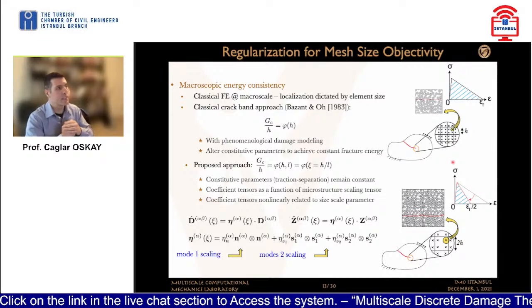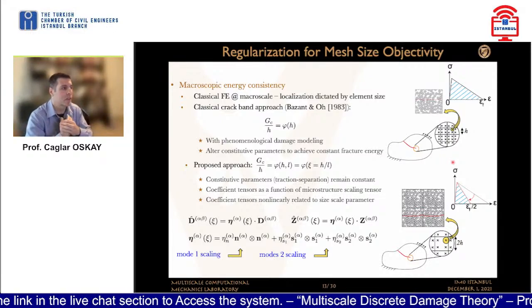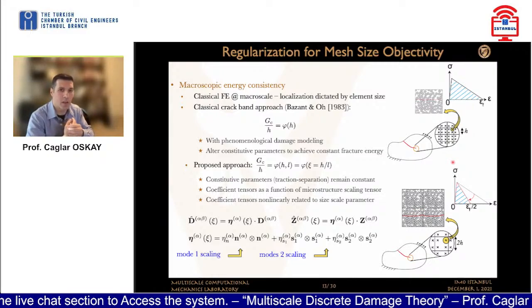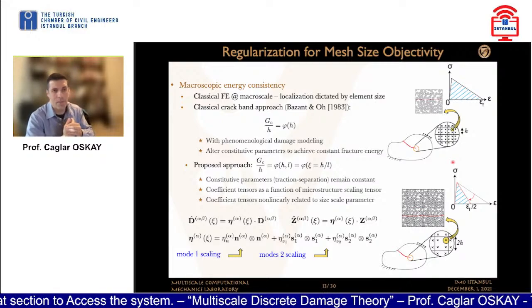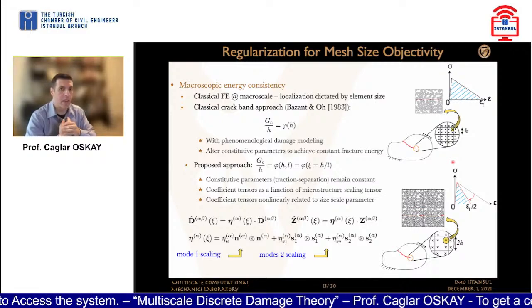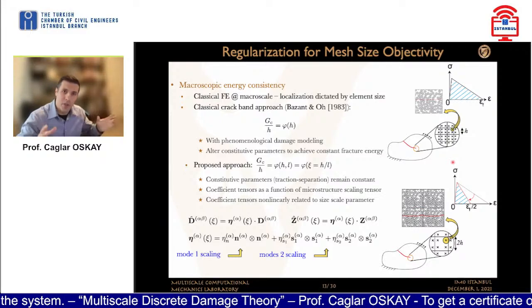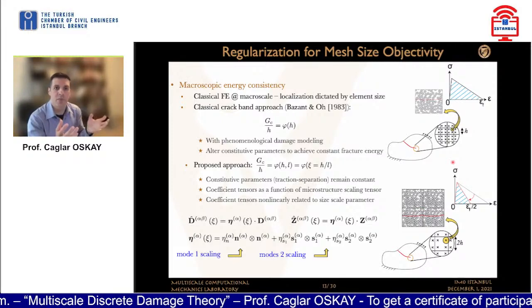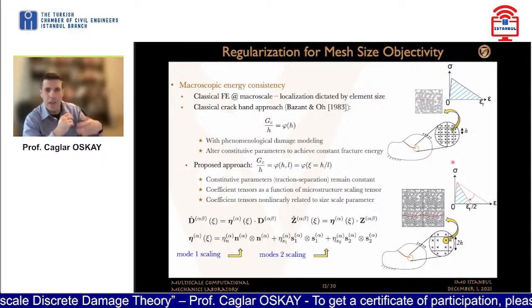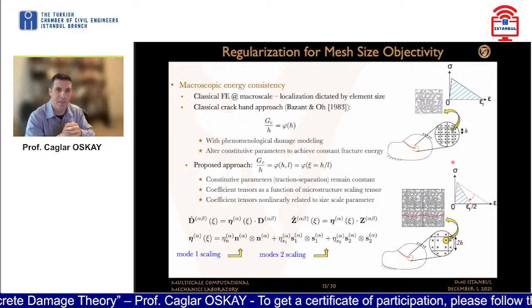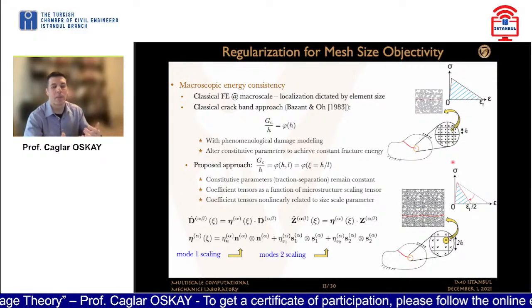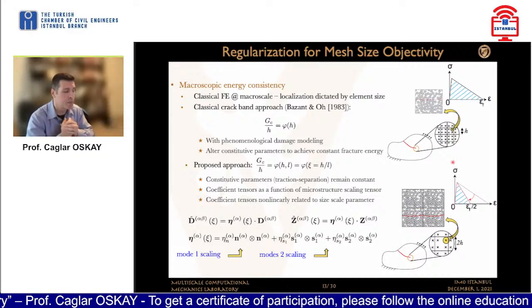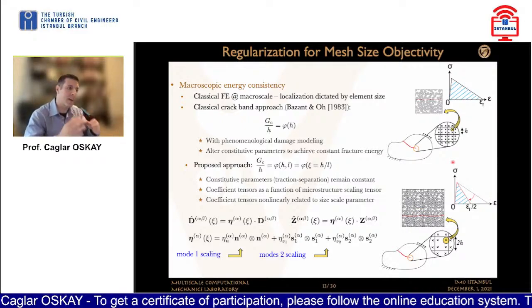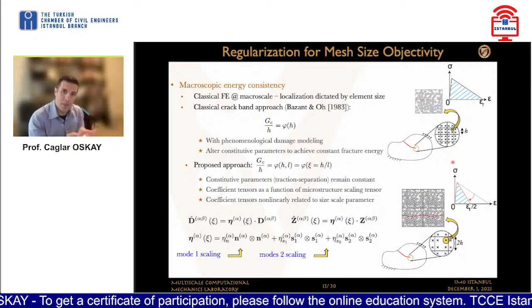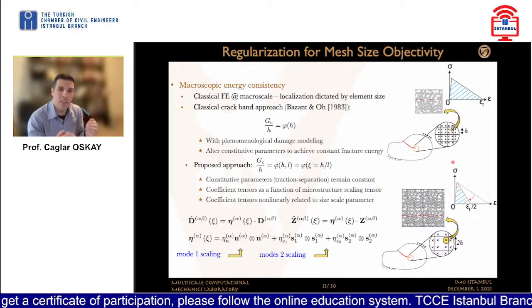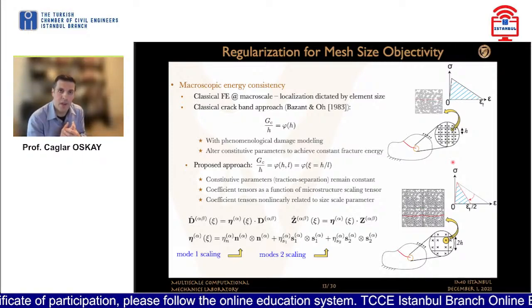The second issue is the regularization to ensure mesh size objectivity. Some of you who are working with concrete materials may be familiar with the classical crack band approach, which was proposed originally by Zdeněk Bažant and co-workers to have an engineering-type solution to this mesh size sensitivity problem. We will follow a similar path in that we will use a classical FE at the macroscopic scale, and we will allow the failure to localize to an element size. In the classical crack band approach, you define the constitutive parameters as a function of the element size in such a way that the overall energy dissipation remains constant regardless of the size of the finite elements.